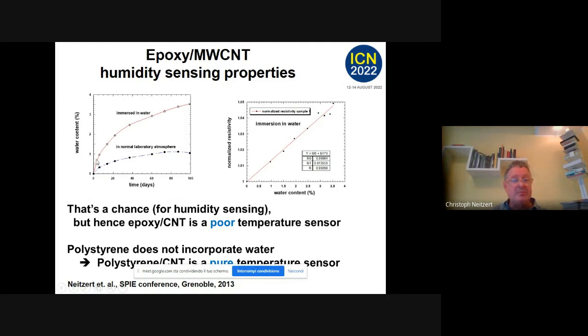A lot of times we measured the weight, the water content, and the water content went up to 3.5%. And you see, this is the uptake of water content, and we see the change in resistivity, and the resistivity increases almost linearly with water content.